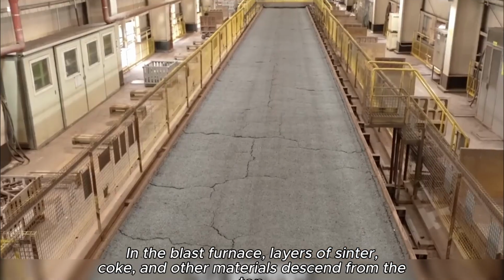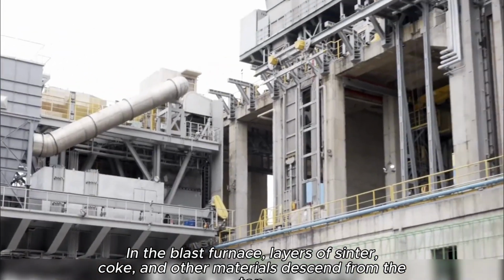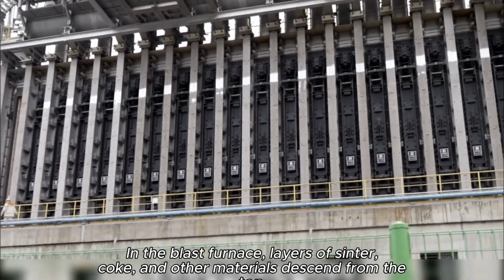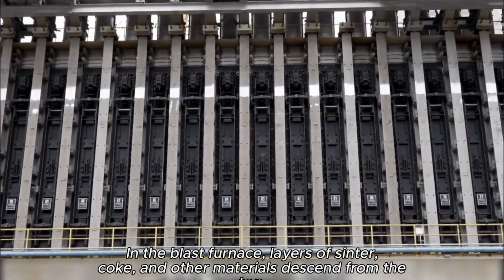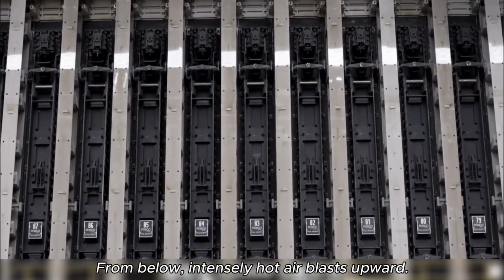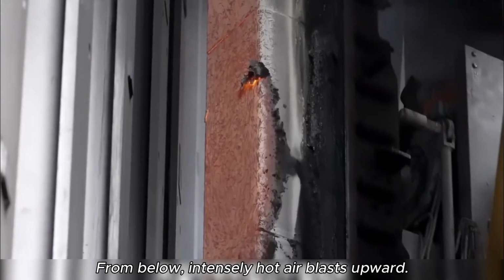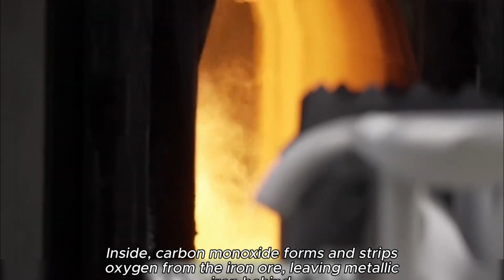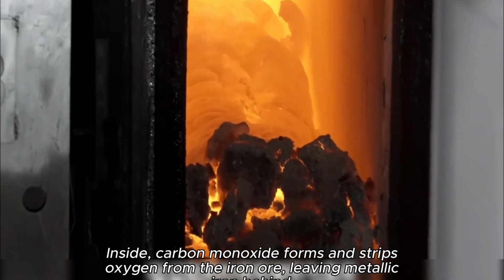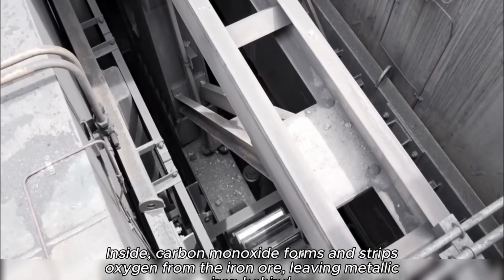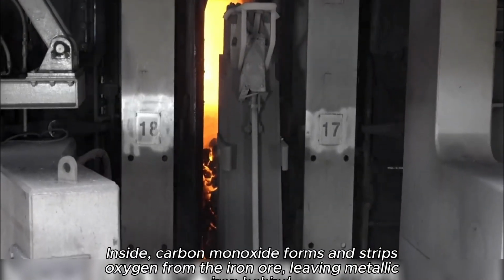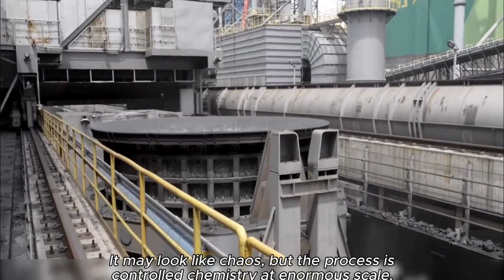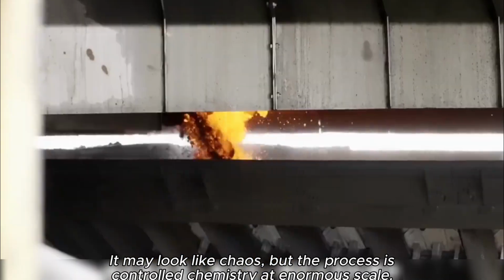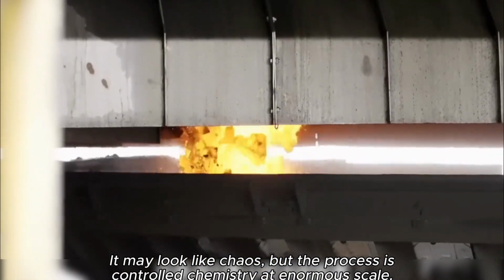In the blast furnace, layers of sinter, coke, and other materials descend from the top. From below, intensely hot air blasts upward. Inside, carbon monoxide forms and strips oxygen from the iron ore, leaving metallic iron behind. It may look like chaos, but the process is controlled chemistry at enormous scale.